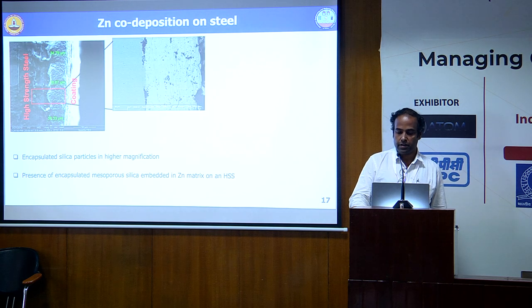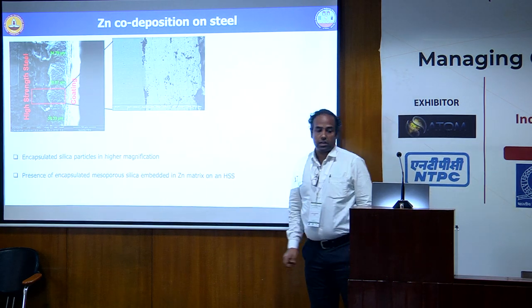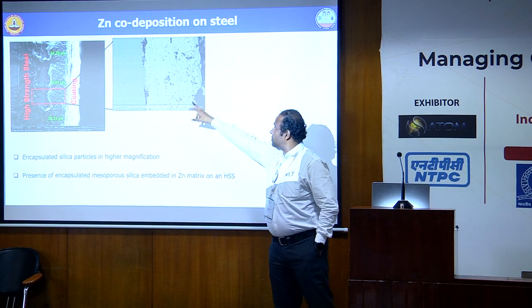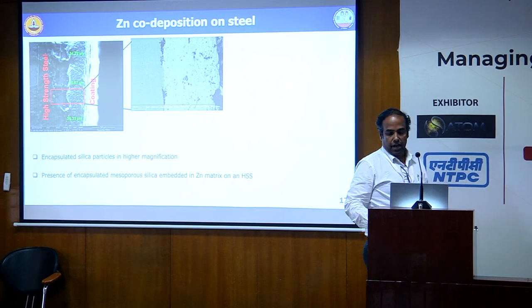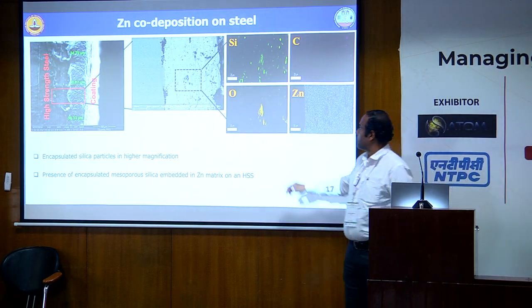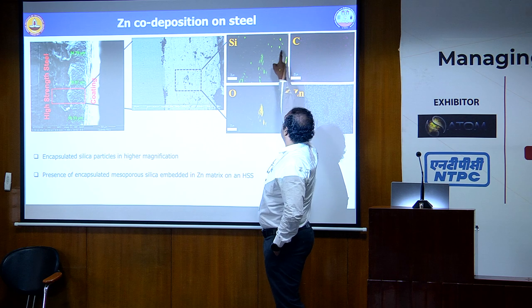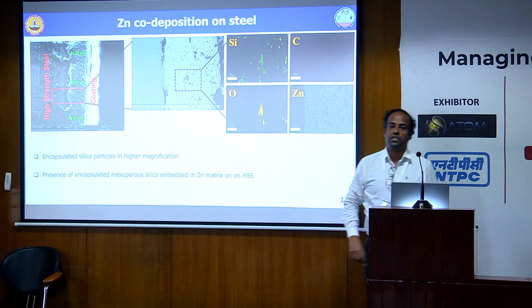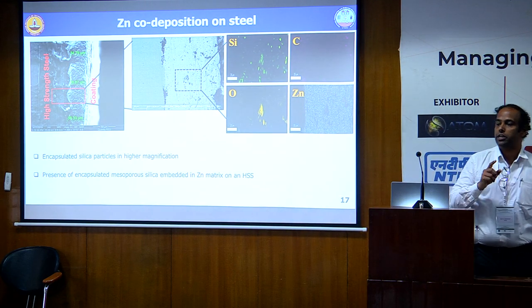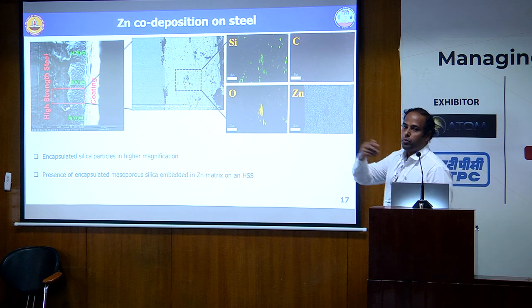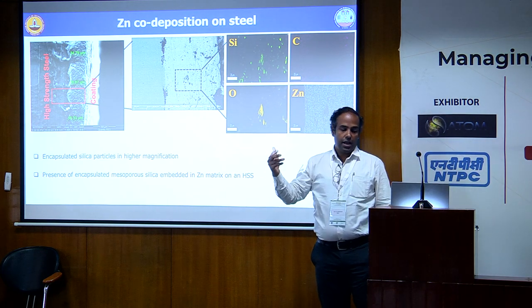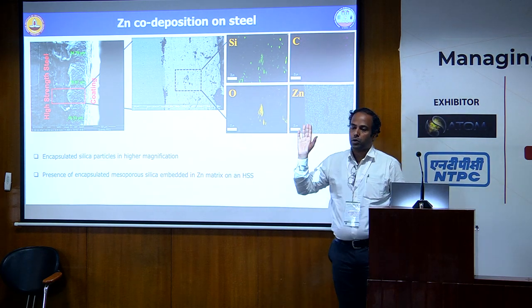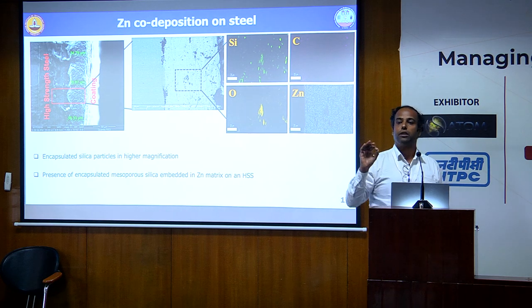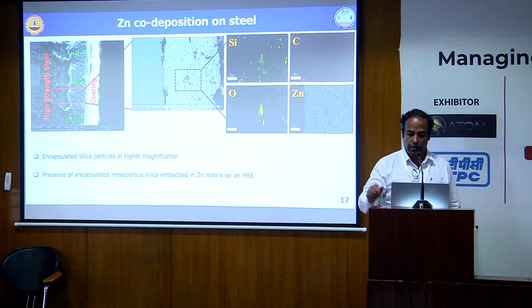What we did, we zoomed at this part of the coating at the cross section, and we looked at this using the EDS imaging. If you look at this particular point, there is a random distribution of silicon and oxygen, which suggests that these particles, which I tried to electro-codeposit, distribute randomly within the coating. We could prove that, yes, we are able to randomly distribute them along with the zinc matrix. It is not just on the surface.